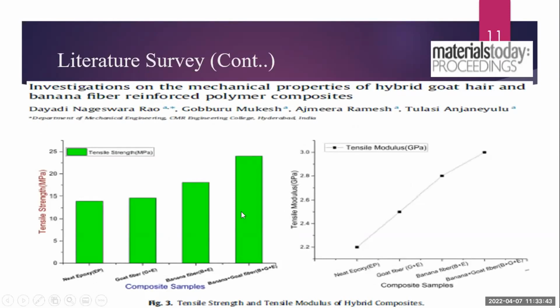Here is a paper published by Dayadi Rao, in which they investigated the mechanical properties of hybrid goat hair and banana fibers. Here they did not use only pure hair in the polymers. They mixed hair as well as banana fibers, and they mixed these two fibers into a polymer composite. Here they used epoxy for mixing these fibers into the polymer. The test result shows that if only pure epoxy is used for fabrication, it gives very poor results.